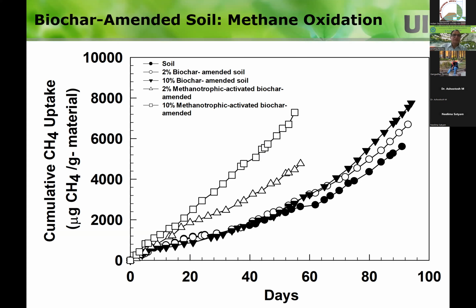Here, we took the soil and did the testing. You can see with time how methane uptake happens. You can see the microbes are there and they keep on taking up the methane. And then we did 2% biochar amended soil, the open circles. You see that there is not much difference, and then after some time you see a deviation. Basically, when you add 2% biochar amended soil, there is a lag time for the methanotrophs to acclimate to the biochar that is present. The time where you don't see much difference is the acclimation.